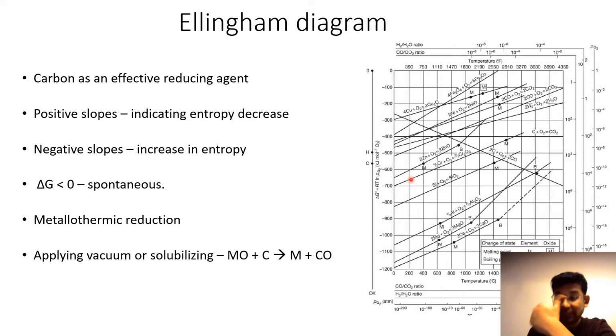When the oxide is very stable, it has the tendency to be more of an oxide. So this is a place where the oxides are very stable, not the metal. Only after a huge increase in temperature, or with carbon, can you produce back the metal. So we have components here, and iron is mostly somewhere around here. The components which are more stable are going to go into the oxide phase because they prefer to form these oxide phases, whereas iron can form the metal. So that's the chemical basis of the EAF steelmaking.